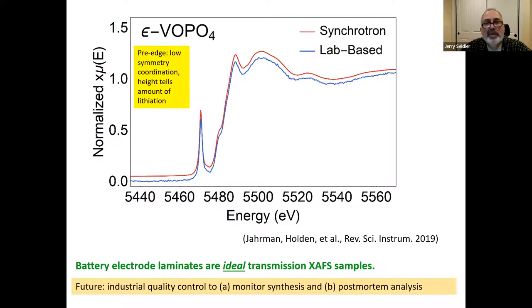We also went on and studied many other kinds of battery laminates, and there's a variety of information here we needn't go into. Again, the agreement with synchrotron is extremely good. But the key thing we learned here was that battery electrode laminates typically are ideal transmission XAS samples. They have large but not too large edge steps. You put them in the beam and things just work. And that certainly suggests that you can monitor synthesis, or let's say post-mortem analysis after battery failure, to see the status of electrodes.